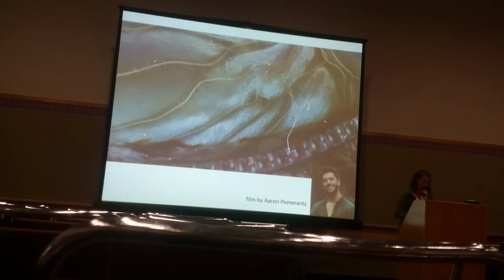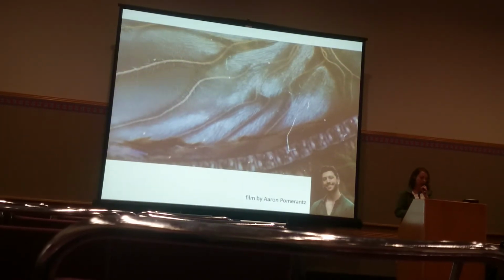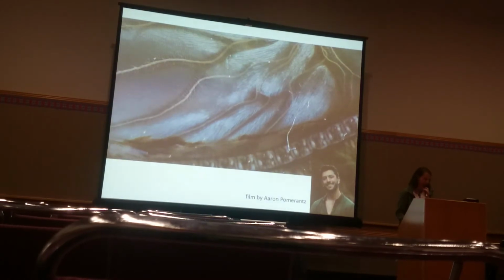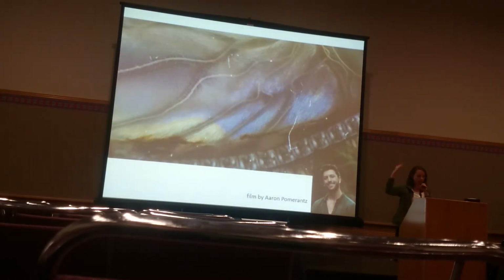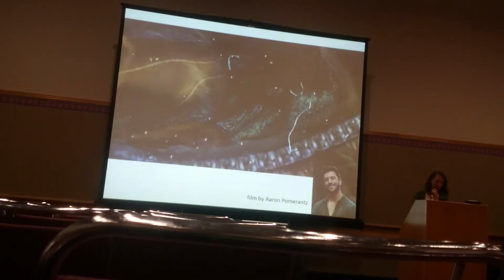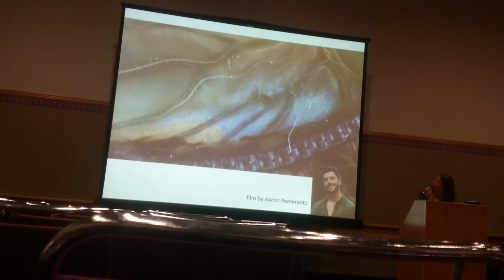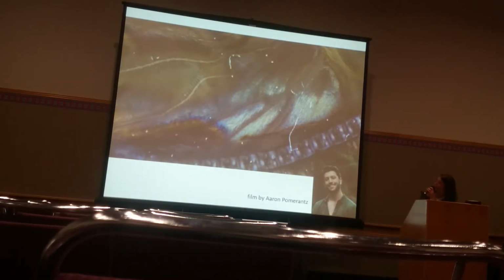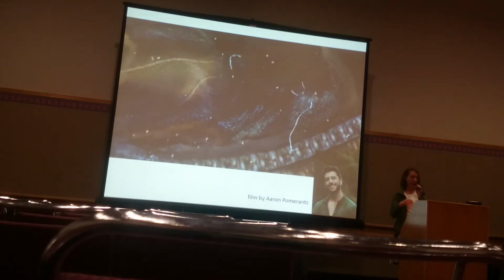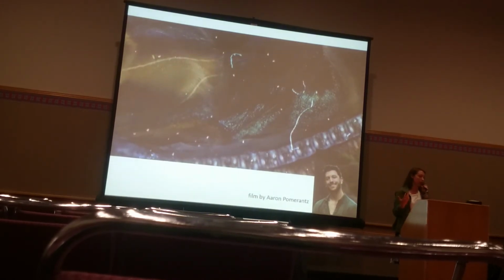So I'm going to play it again, zoomed in there, just starting when chitin's first starting to be deposited. And I want you to watch this region. You're going to see it shift like a rainbow in exactly the order that we would predict. As thickness increases, the color would shift. Maybe that went too fast. I'll play one more time. We start kind of gold, purple, and then blue, and then increasingly greener and greener until it's turquoise. So again, this suggests that chitin gets deposited gradually. It's not that you can have X or 2X units of chitin thickness, but that developmentally as well, probably any thickness or therefore any color is possible.